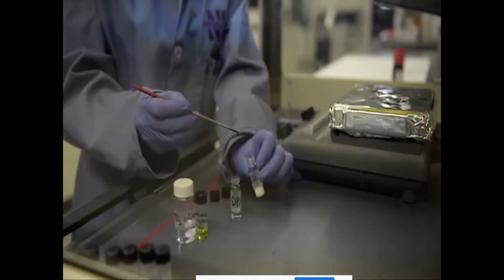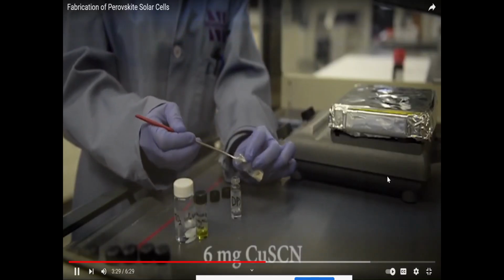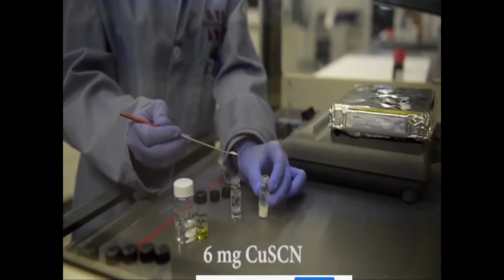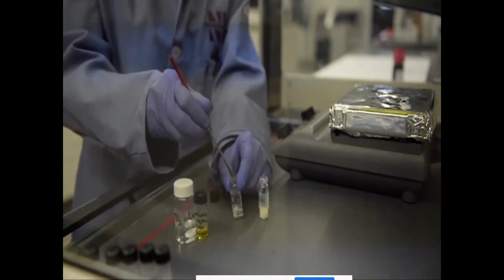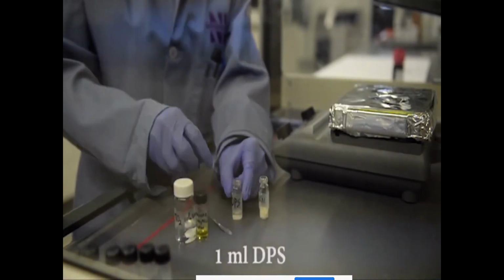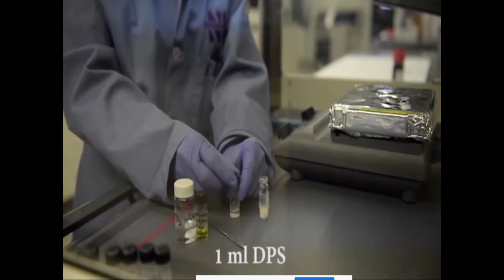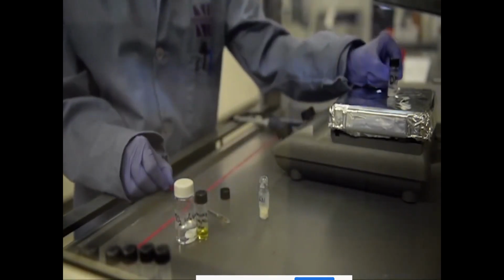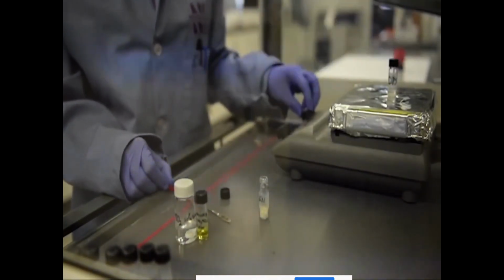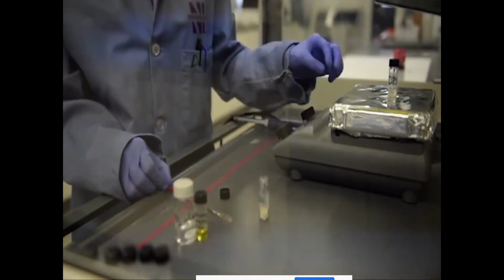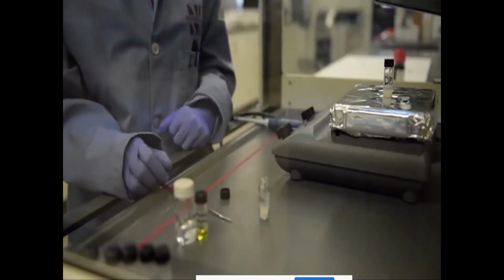Lastly, we will make 0.05 molar copper thiocyanate solution by stirring 6 mg of copper thiocyanate powder in 1 milliliter of dipropyl sulfide solvent at room temperature overnight. The final solution should look colorless and transparent.